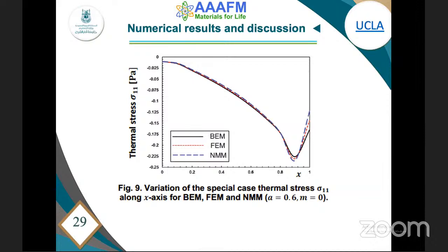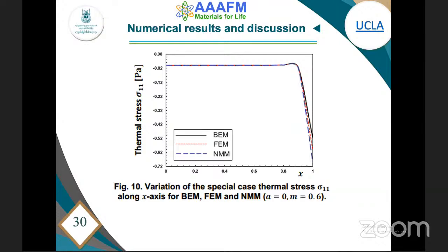In order to validate our results with the suggested method, we compare our results for a special case with finite element results and the normal mode method. We get good agreement with other results for the boundary element method. Also sigma 11 for different methods, BEM, FEM, NMM, where fractional order equals 0 and functionally graded parameter 0.6.